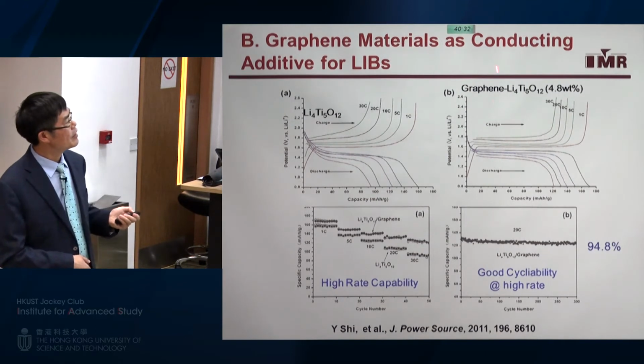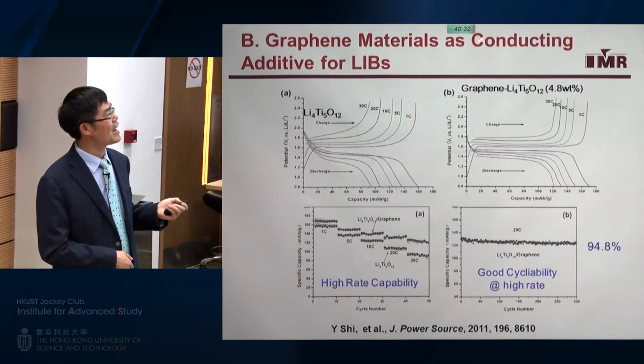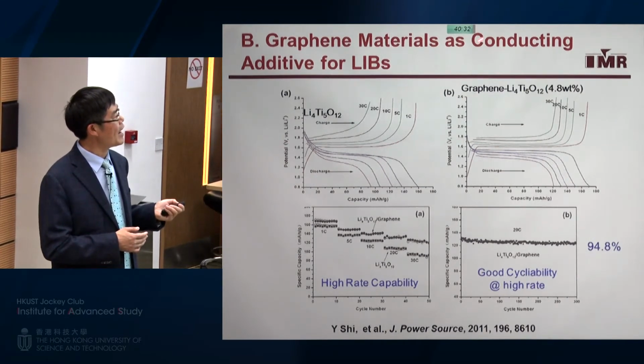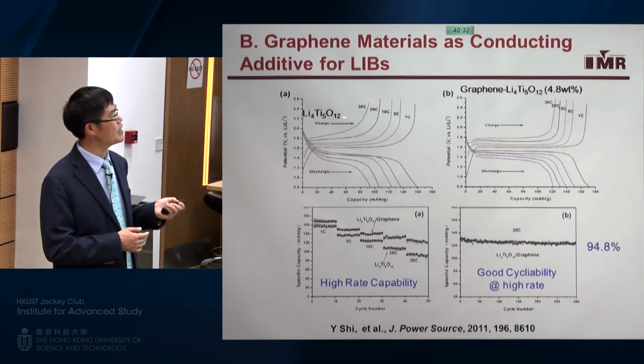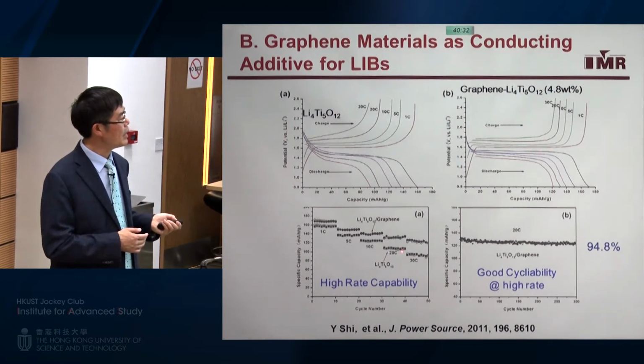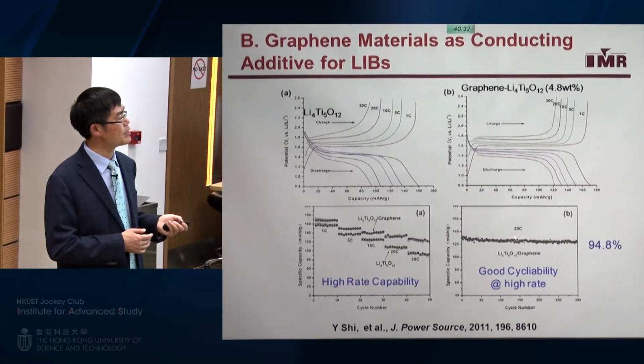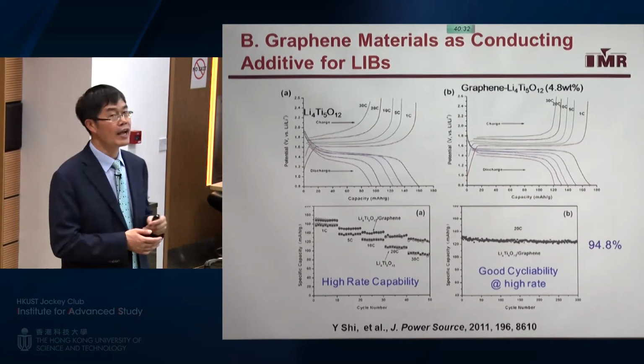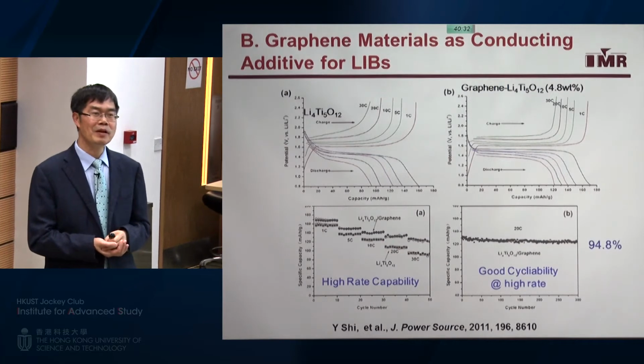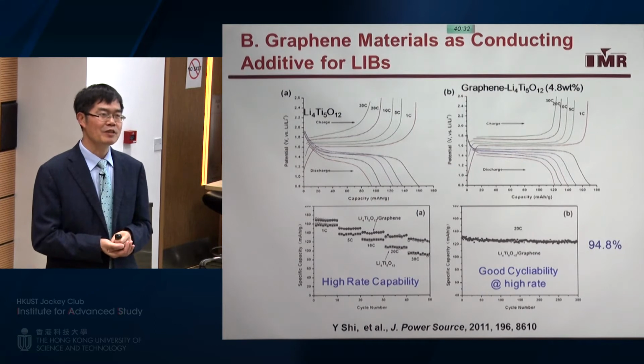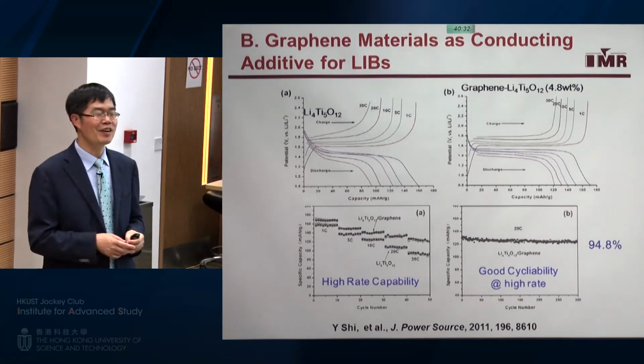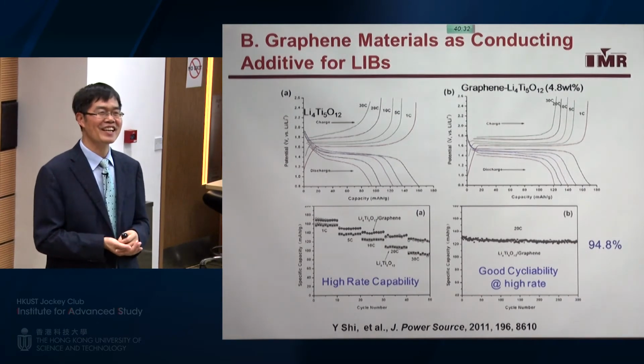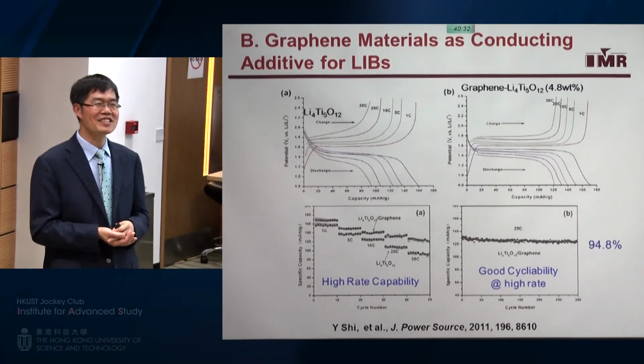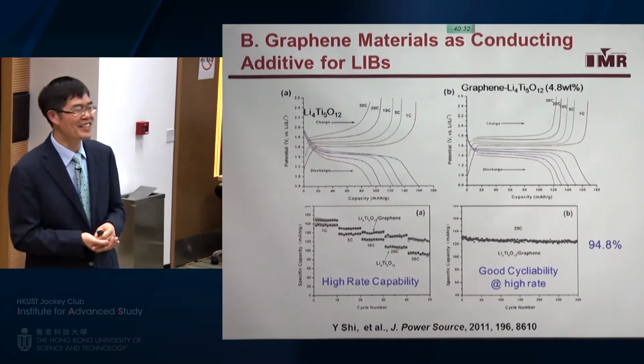Another approach is like graphene as a conducting additive. As I show you, we can add this graphene material into lithium titanium oxide to reduce the polarization and improve the capacity and also cyclability. Here I show you this 20 C rate, which means 3 minutes charge and discharge, we still can have very high capacity. So therefore, maybe you have heard many news from mainland China. Some battery companies are using graphene in batteries. Yeah, we can improve the performance of batteries, but not as significantly as some companies claimed. Charging 10 minutes, the electric vehicle can drive 1,000 kilometers. That's nonsense.